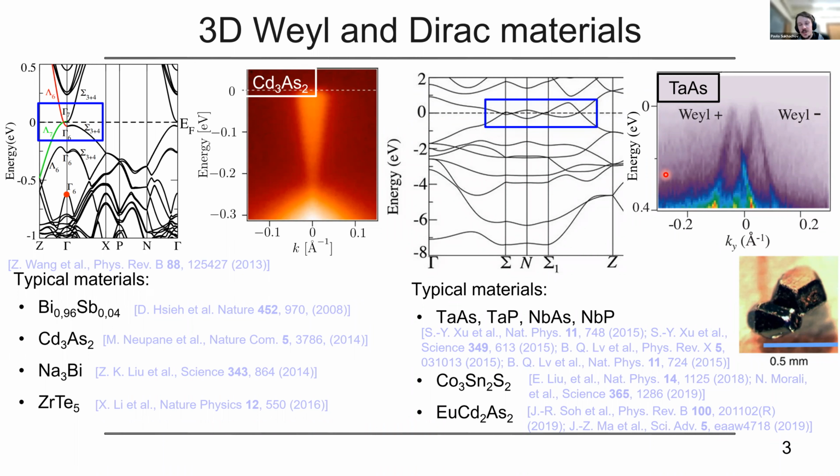But even going beyond the theory, I would say that the main effect, which is a reduction of sound attenuation, should remain the same, even though we have a larger amount of Weyl nodes. Weyl nodes will just contribute additively, so there is no dependence on the relative orientation of nodes here. Of course, there might be some corrections related to the fact that we scatter not within the pairs but between different nodes.